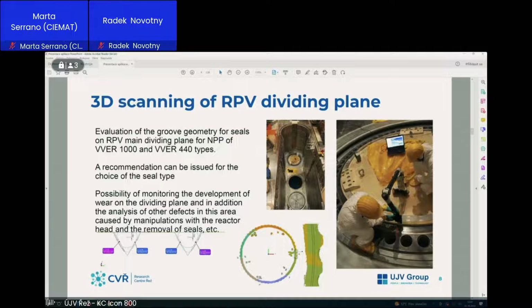We must be careful because we are in a radiation area. And you can also see that colleagues, sometimes also me, we had to use Tyvek, so it was not, let's say, a friendly condition for operators, for us. Here on the left bottom, you can see the results. There is some wear of the groove geometry, and the outputs of our measurements are used for the lifetime assessment of this part of the reactor pressure vessel.